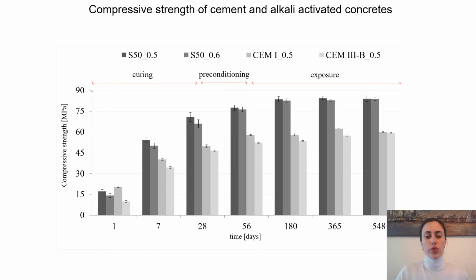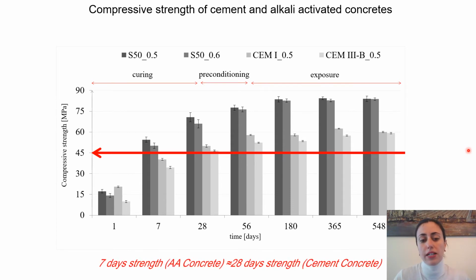Now, when it comes to results, what we can first see here is that the strength is studied for a period of 548 days, and as you can see, the strength is developing also after 28 days. Here we had curing prior to carbonation for 28 days, then preconditioning, and then exposure to carbonation from day 56. The strength of alkali activated concrete in this study is higher, and you can see how much here. Why is that? 7 days of alkali activated concrete corresponds to 28 days of the cement-based concrete.